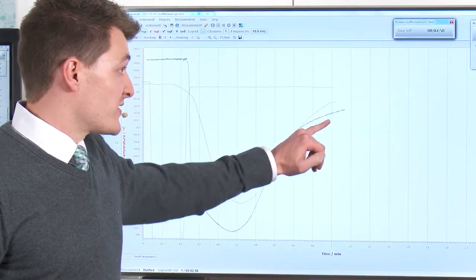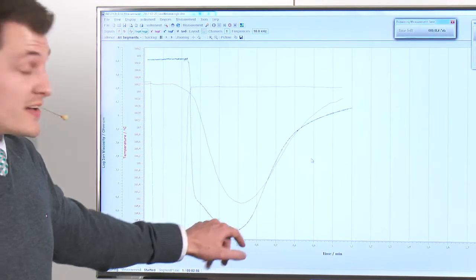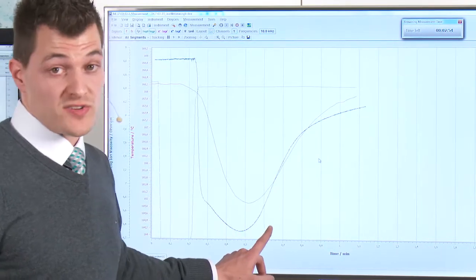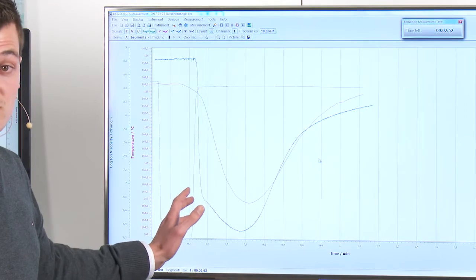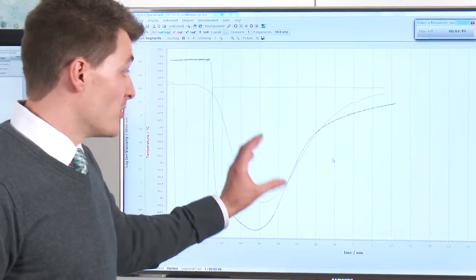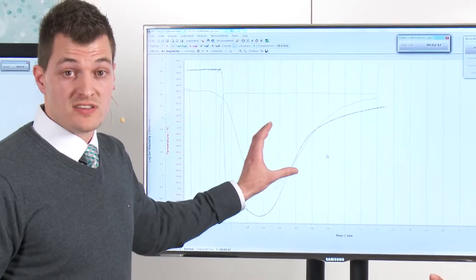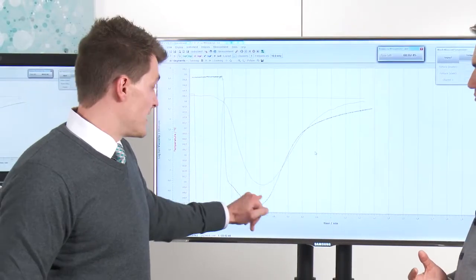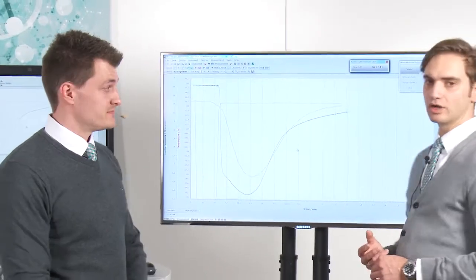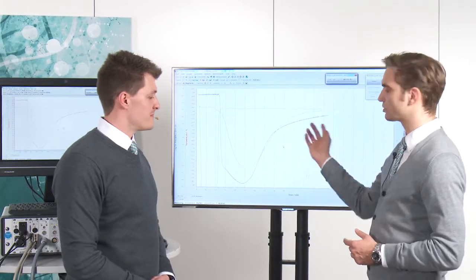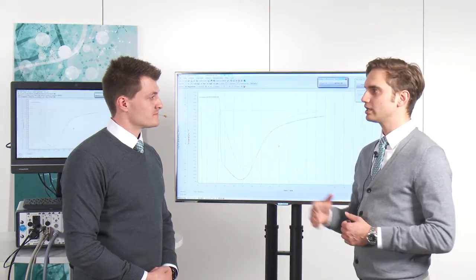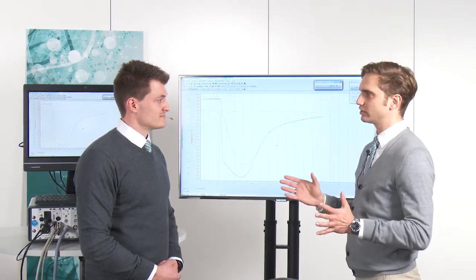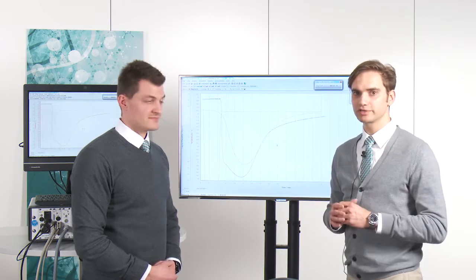Now you can see that the ion viscosity is increasing and increasing. The slope of this increasing ion viscosity gives us information about the reactivity of this material. So the slope is directly correlating to the reactivity, so the speed of cure at each point we measure here. Okay, so we can just follow the curing as it goes along, but Alex, I have some more questions to you because maybe this went a little bit quick for the viewers.